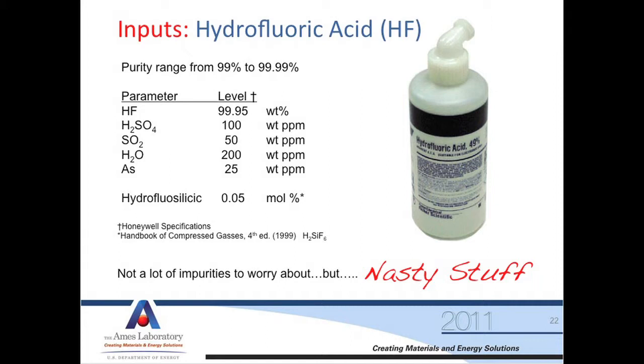The last input I'll talk about is hydrofluoric acid, which we use for our process. This is a bottle of HF in water, but we use anhydrous hydrofluoric acid. From this chart, there are not a lot of impurities of concern for us. We pull the HF off as a gas, so it comes off very clean. There may be some carryover, and we don't see any arsenic in it. The problem with HF is it's really nasty stuff, and you have to give it the respect it's due. A lot of commercial entities don't use anhydrous hydrogen fluoride because it's just not fun to work with — it's expensive and dangerous. If there's an easier way, such as an electrolytic method or using ammonium bifluoride to convert hydroxides, they'll use that instead.